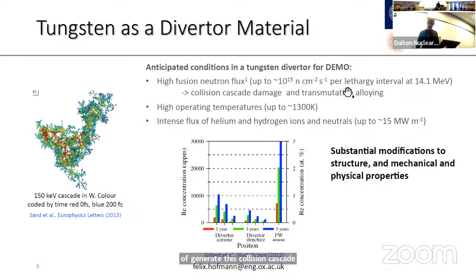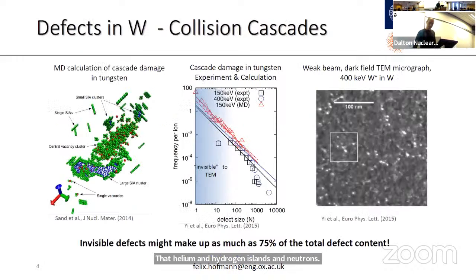And you also get some transmutation alloying, which means that what started out as a pure tungsten block soon won't be a pure tungsten block anymore, but will have all sorts of alloying elements inside it. You'll also have high operating temperatures and an intense flux of helium and hydrogen ions and neutrons. So all of this can substantially change the properties of the material. And what we've really focused on is the role of crystal defects in all of this.